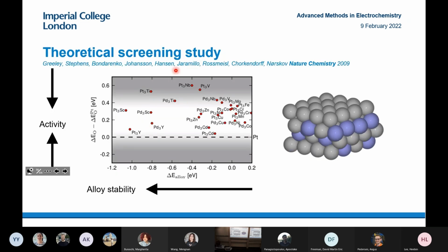So actually, working with Jeff Greeley, Heine Hansen, Jan Rossmeisl and Jens Nørskov, they did a screening of many different alloys, and they were trying to find what alloys could be less susceptible to de-alloying, have very negative alloying energies, the same as enthalpy of formation, and at the same time have the right oxygen binding energy. And these are the outputs of their screening study. They looked at many thousands of alloys, all platinum overlayers, similar to the platinum copper near surface alloy I showed before.